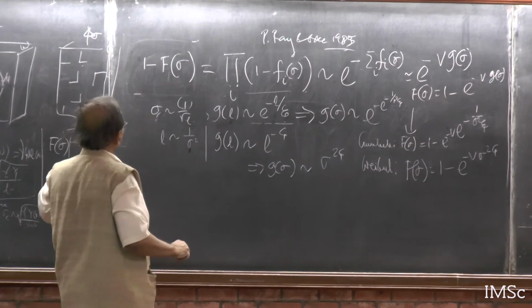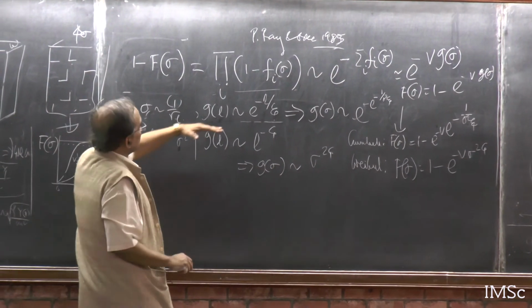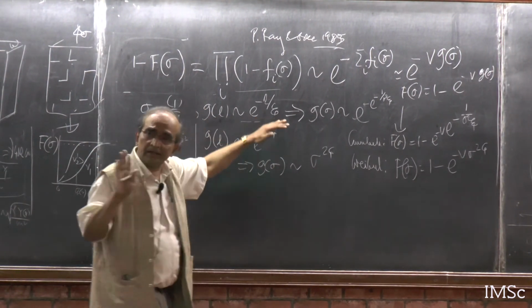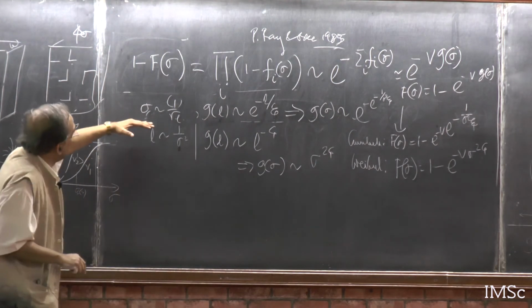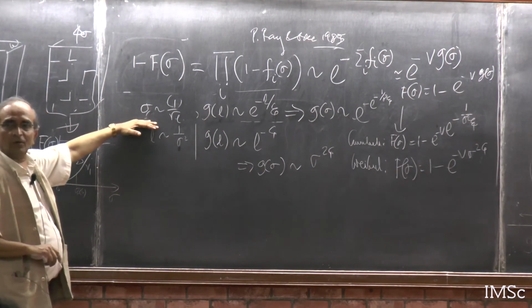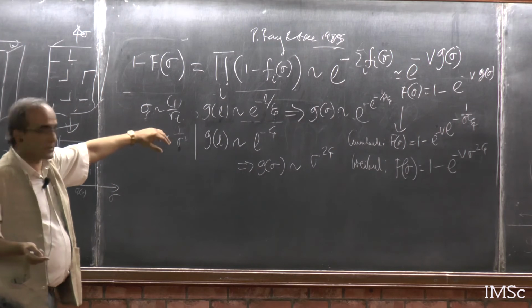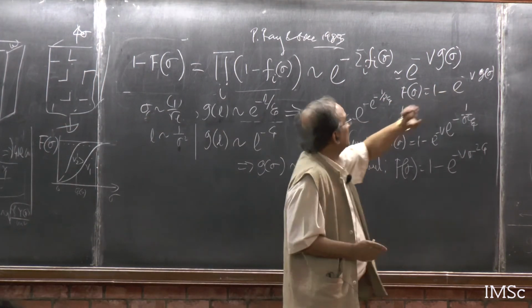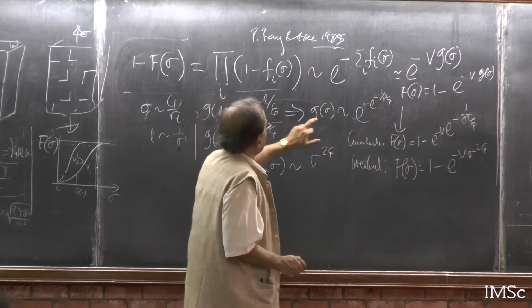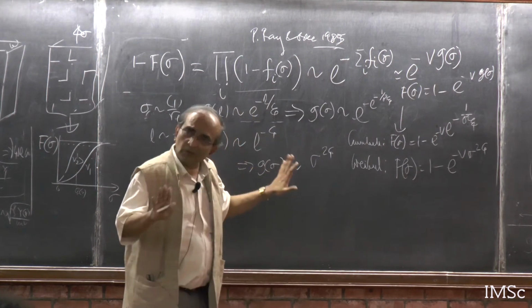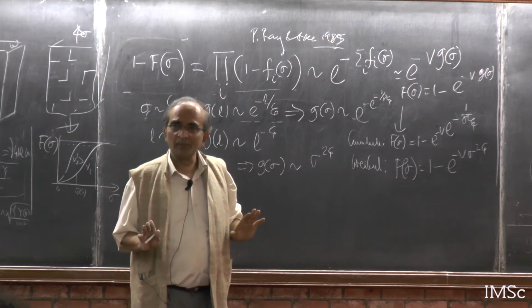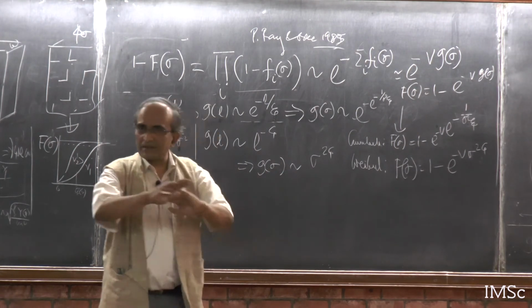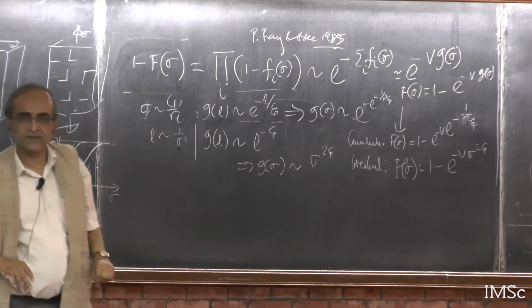Here I did approximations, and then one approximation is that you are using the picture from Griffith's estimate. Because I need G sigma, I got only GL, and that too exactly using percolation, which is exact in one dimension. Otherwise you cannot do exact things.